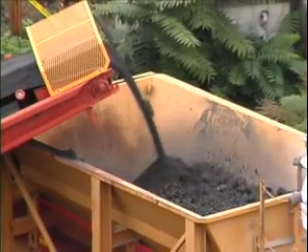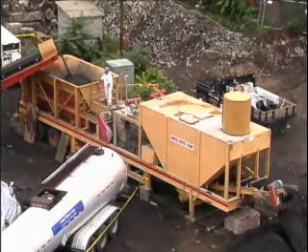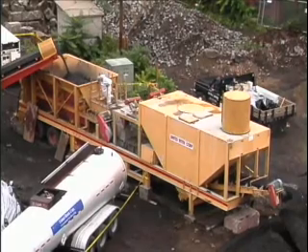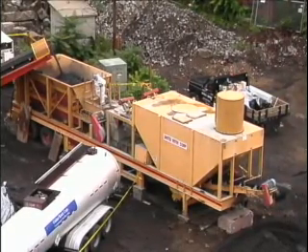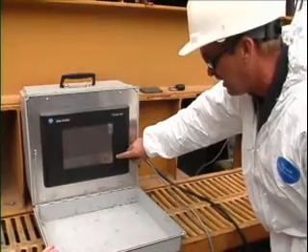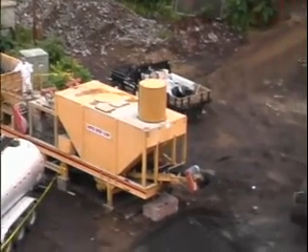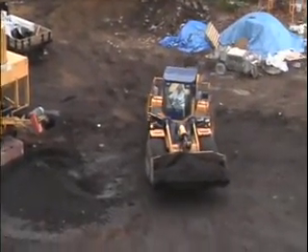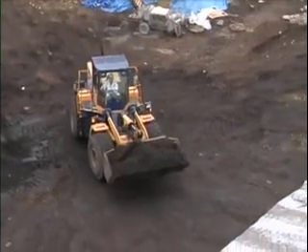Screened material is conveyed to the pug mill hopper. Inside the pug mill, twin rotating shafts with paddles mix the contaminated soil with Portland cement. What we're doing today is we're adding Portland cement into it to hydrate the product and give stability and take the TCLP levels of the lead down below a non-detect. Computer controls on the pug mill assure that the proper amount of cement is added to the soil. Treated soil exits the pug mill and is staged for reuse as pavement base.